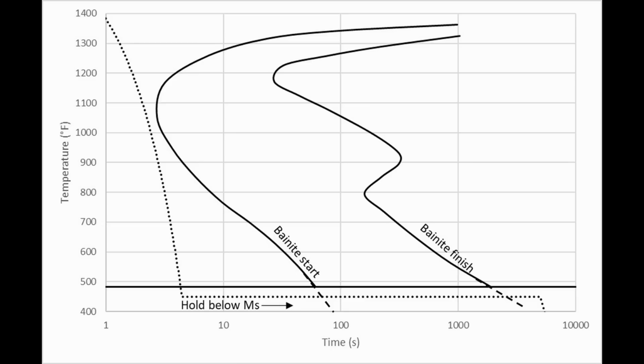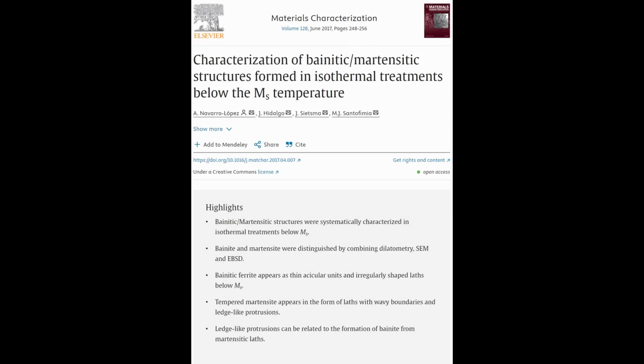One thing to note is that some metallurgists disagree about what is transforming at this lower temperature. Some people say that it's not bainite, but it's some type of isothermal martensite. Normally, martensite forms only with temperature. It's called an athermal transformation. The lower that you cool the steel, the more martensite forms. But if you hold under martensite start, you often get a transformation that occurs.